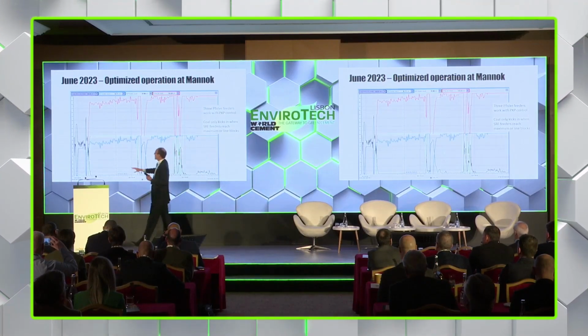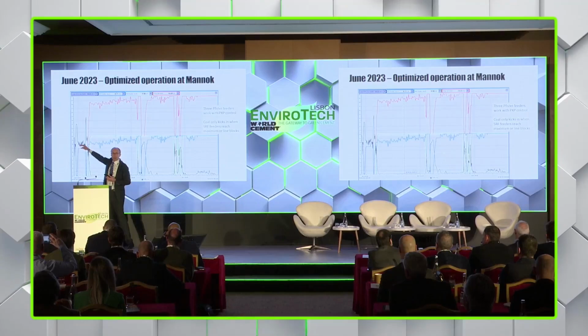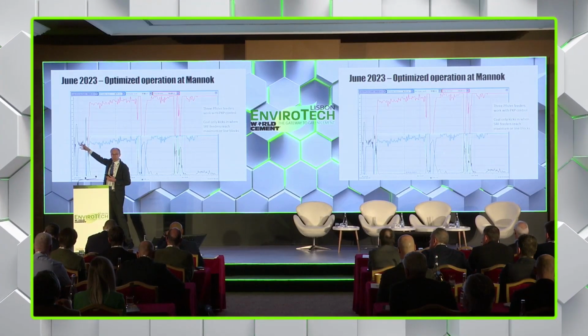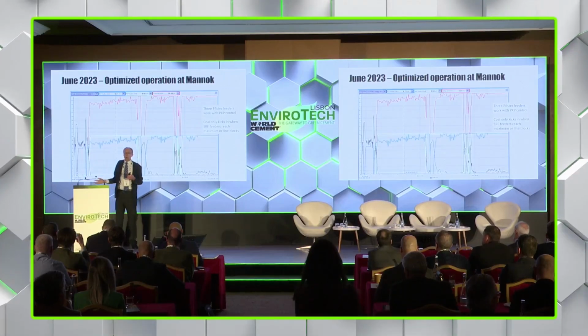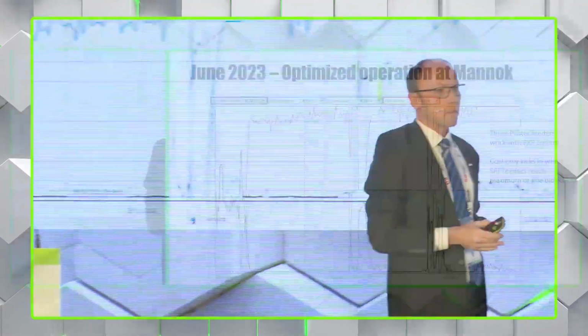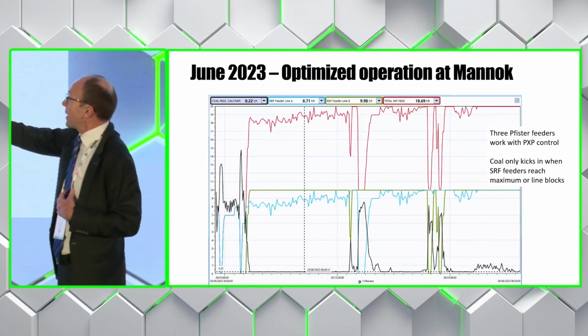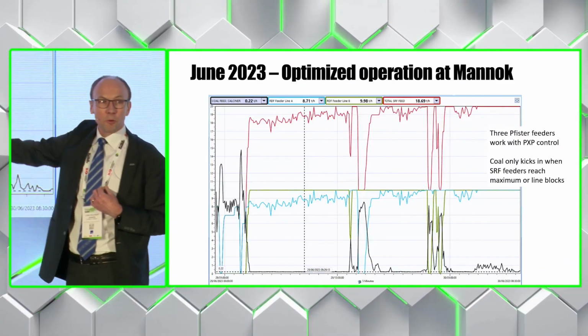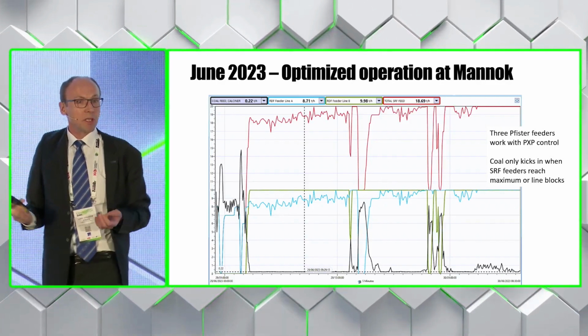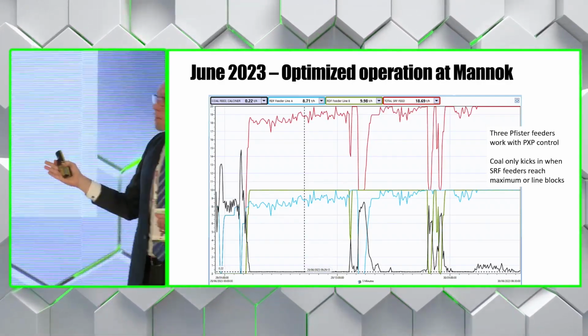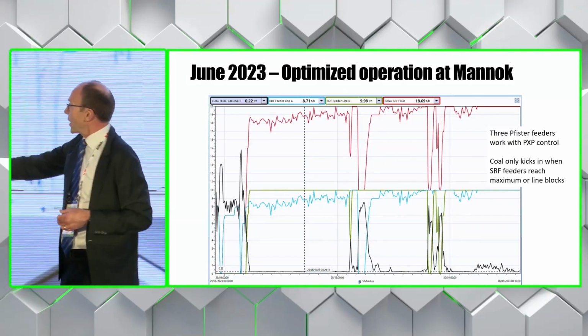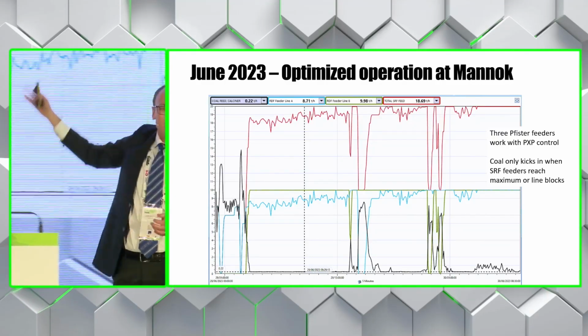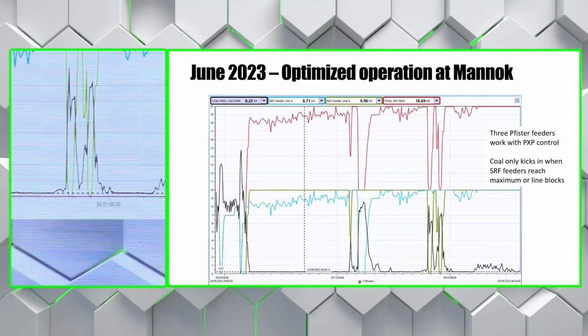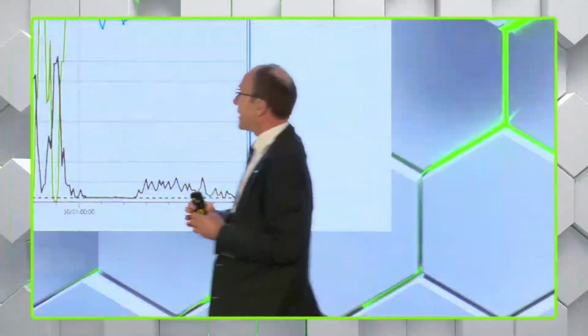If we start over here, we can see that they're firing about half of the fuel in the calciner being alternative fuel and the other half being coal, both being fired directly to the calciner. At that point, you see that when the alternative fuel blocks, the coal takes over, so firing about 13 to 15 tons per hour of coal in the calciner. At this point over here, we then put on the FUELFLEX Pyrolyzer, putting in 10 tons per hour of alternative fuel into the FUELFLEX Pyrolyzer, and we then see the coal going right down to 0.2 tons per hour, so minimal coal in the calciner.